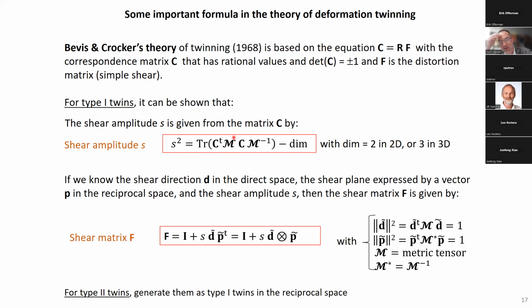I will not detail, you can calculate the metric tensor nearly immediately from the lattice parameters. So you can, if it's cubic, the metric tensor is identity. Okay, so if you apply this relationship, you can calculate the shear amplitude. Okay, and from the correspondence, you can also calculate the shear direction. You can calculate also the shear plane, and with that, you can calculate the shear distortion matrix related to the twinning. Okay, I do not detail.